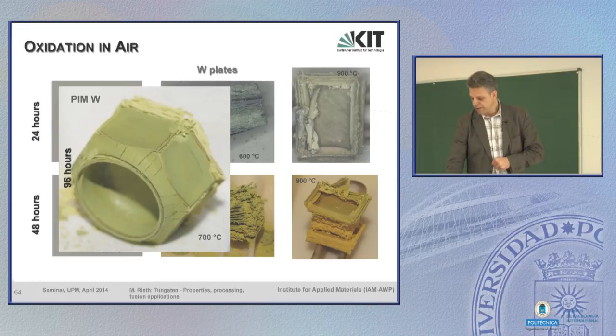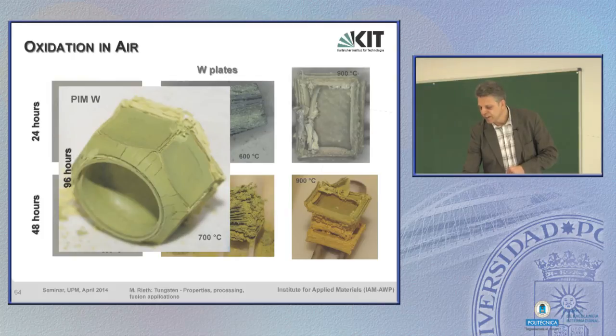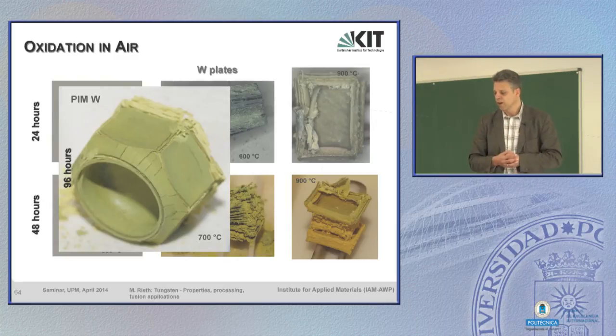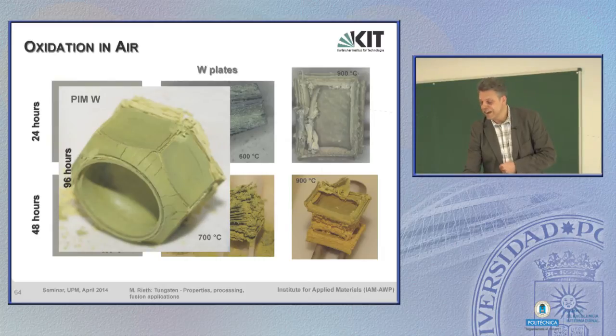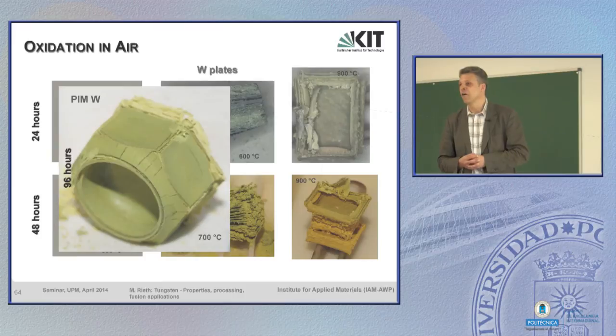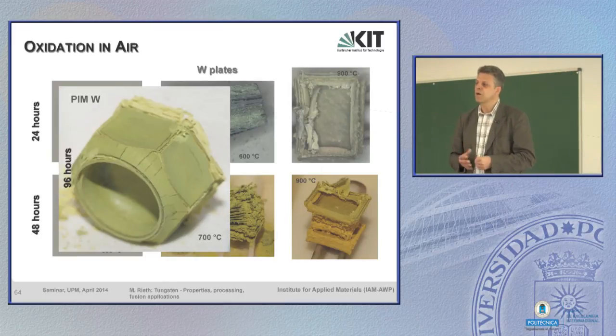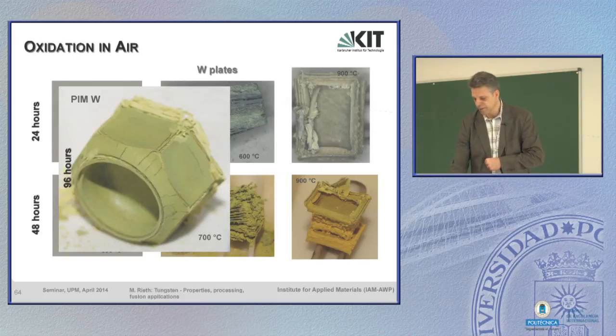And we have done the same for this powder injection molded part, and even at 700 C and even after 4 days in the furnace in usual air, well, it oxidizes, that's clear, but you can still recognize at least the original shape. So it seems that also here, powder injection molded tungsten parts show at least some advantages.